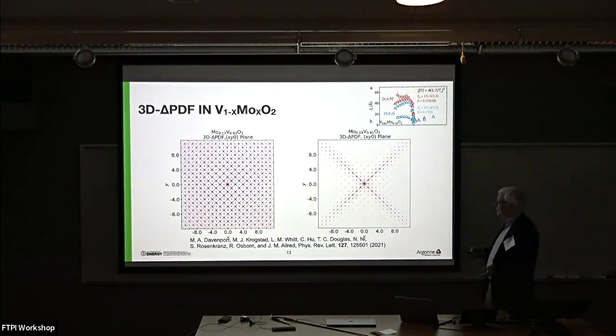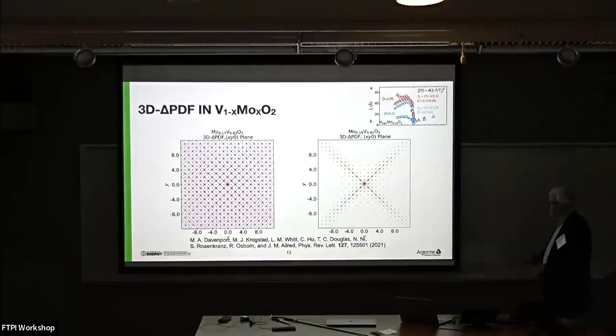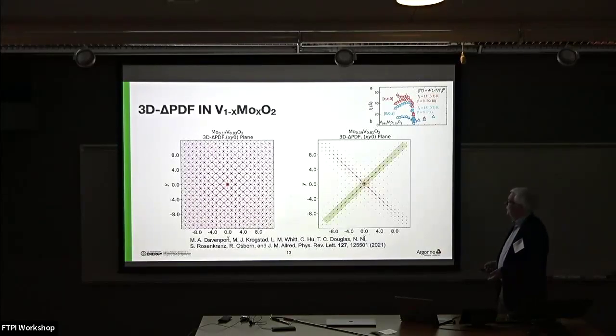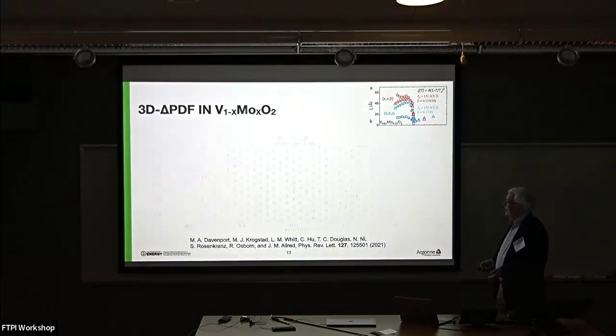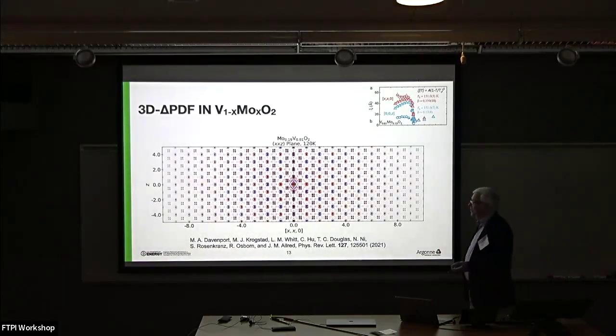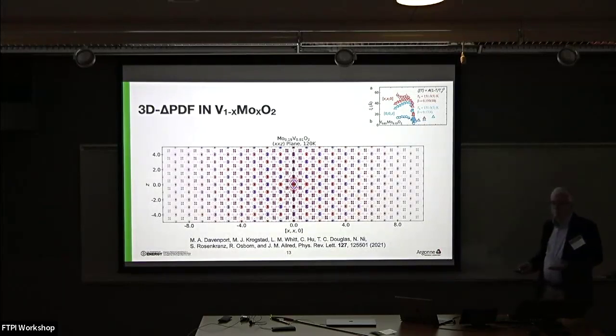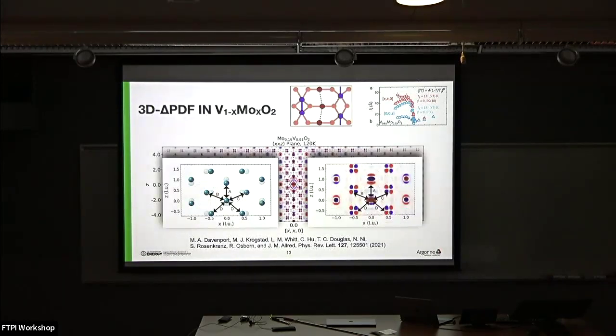So we have these quasi 2D planes, and to understand what those planes look like, we have to go along the planes. If we look at the 3D delta PDF, we get what apparently is a very complex pattern, but again, they are discrete interatomic vectors. And just as in the sodium titanate, you can essentially read off what's going on in the structure just by looking at what connects the red peaks and ignoring the blue peaks.